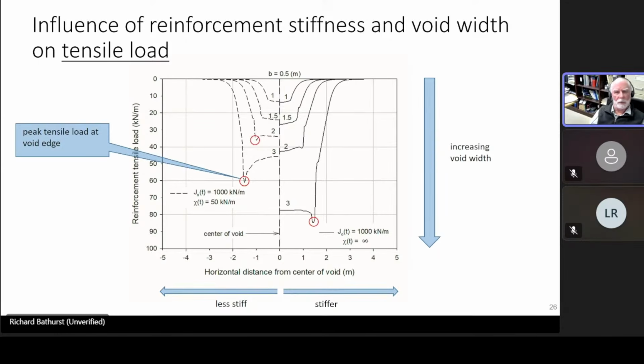The other interesting thing you can see here is that the peak tensile loads do not always occur at the center of the reinforcement. As soon as you get above a void width of about a meter, you can see that the maximum loads in the reinforcement were actually at the edge. And this is a phenomenon that you cannot capture using an analytical method of the types that I've mentioned earlier.